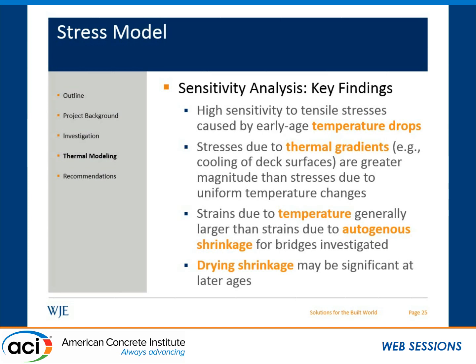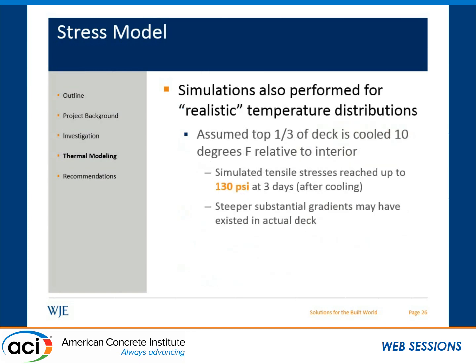And finally, we found that drying shrinkage might be significant at later ages, though it's not really important at the earlier ages. Finally, once we had done those sensitivity analyses, we did some "approximately realistic" temperature distributions. I'm putting that in quotes because we don't really know what the situations were like at the time of the bridge construction, so these are just approximate, but they're more realistic than assuming an arbitrary number.